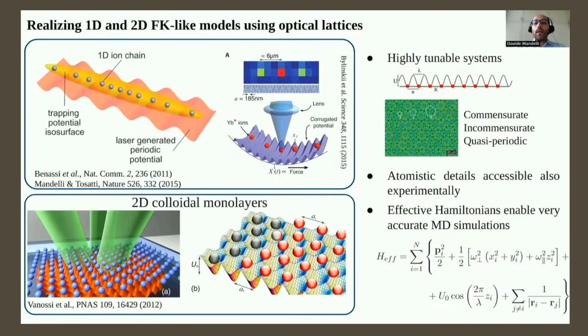there is also the possibility of exploring exotic interfaces with quasi-periodic substrate potential. Second, even in experiments using optical techniques, one can follow the position and velocity of each single particle. So even experimentally, one has access to the atomic details of what is going on. And the third point is that there exist effective Hamiltonians that enable very accurate molecular dynamics simulations. So one can perform simulations that match one-to-one with experiments and make predictions that can be tested easily in experiments.